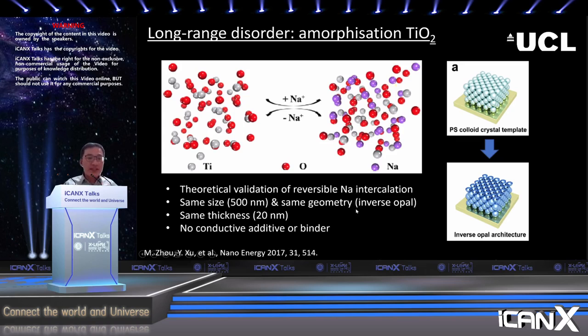And the reason is that we all know there's a lot of variables inside electrode materials: the size of the material, the thickness of the material, and there's also the conductive additive and the binder that are not active to store ions, but have to be added into the material in order to increase the electronic conductivity of the battery. So the reason why we pick atomic layer deposition to synthesize titanium dioxide is that the technology can have very precise control on not only the size of the titanium dioxide, but also the thickness, which is 20 nanometers in our case.